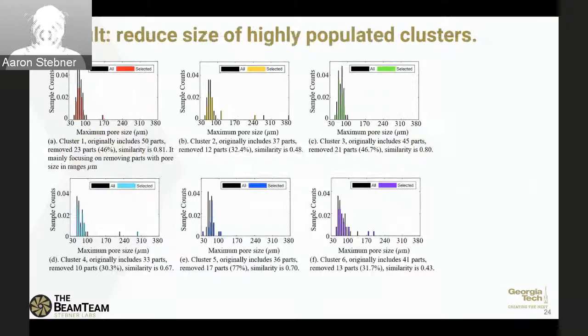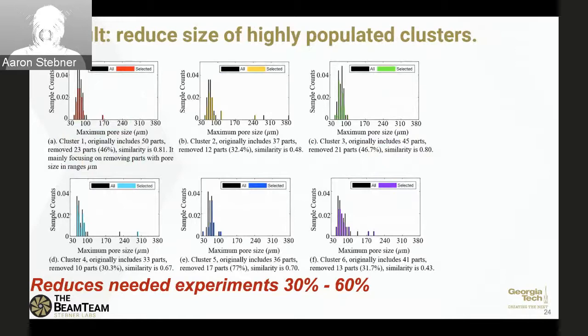Yeah. So the takeaway was that the similarity clustering, using those things we knew a priori, like the laser recoil pressure, the angle to the laser, and number of layers in the part, allowed us to reduce the number of experiments that we needed to have the same statistics as the full database by 30 to 60%. And this project kind of left off there. I think the next challenge is to show, can it work inversely in a sequential learning where we don't know the whole database a priori, right? So there's still a challenge here to take it to the next level that we're trying to work out with a new student now. So let's go to the next slide.